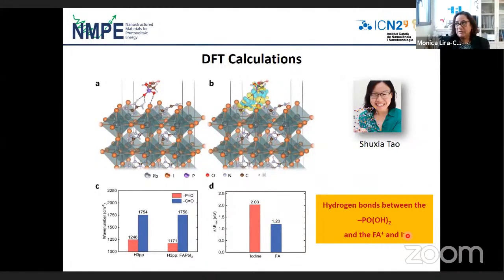Okay, so it was clear for us with all of these experiments that we are passivating, that we are immobilizing ions, and that it's the phosphonate that is making this effect. It's also clear that we are not passivating deep defects, but it means that we are passivating shallow defects. We are not sure yet, so the next thing we have to do is prove finally that there are shallow defects, the ones affecting this result the most.